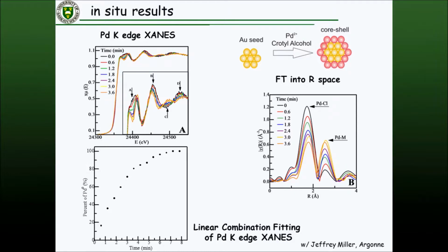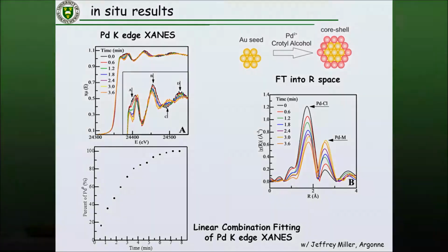And so here is the spectroscopy, the palladium K edge, 1s to 5p transition effectively at the edge. A little bit boring at the edge, but you do see small features at the edge that are changing. And if you come in with standards of palladium-0 particles and palladium chloride salts, you can actually do linear combination fitting, and we can pull out from these spectra how much palladium-0 there is as a function of time. You can actually follow the kinetics of the palladium reduction in real time. And this is really a difficult experiment to do by any other technique.